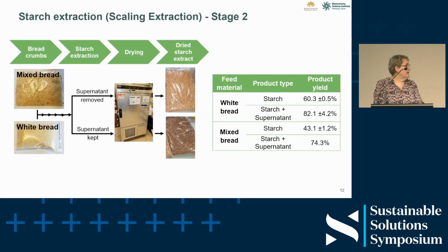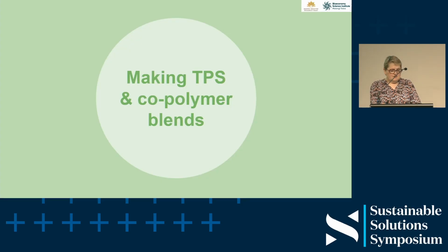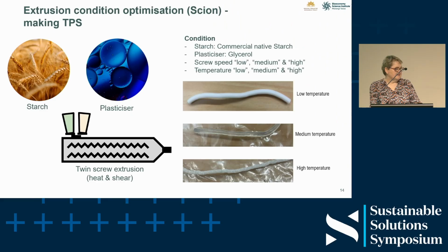So following on from that, we went to stage 2, which was basically scaling up so that we could get enough of the starch to hand over to Scion and see what they could do with it. This worked well with the scaling up, and we obtained good yields. Particularly, we're up to 82% with starch plus supernatant with the white bread and 74.3% with the mixed bread. So this was where Scion took over with making thermoplastic starch and copolymer blends.